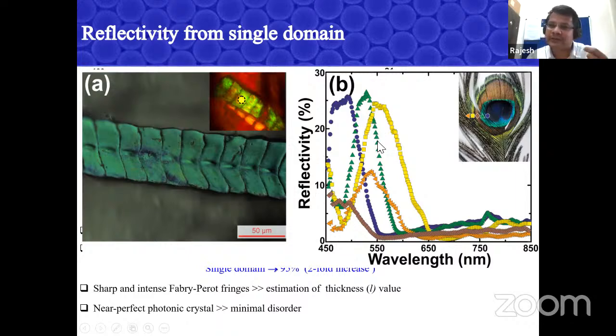Now you can see that this peacock feather is also giving a peak in reflectivity, and that happens because this peacock feather has a photonic band gap, which arises because of the periodic structure in these feathers. So it's a very nice natural nanophotonic system. There are many papers published where people use Maxwell's equations, solve for the peacock feather, and find solutions where you can get a band gap for light.